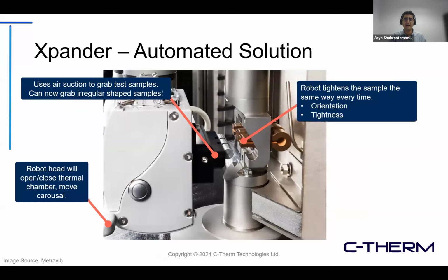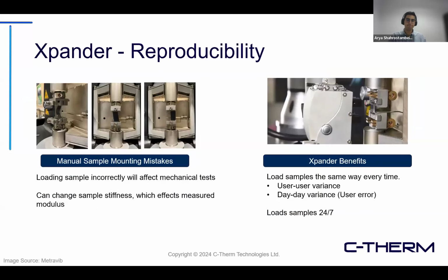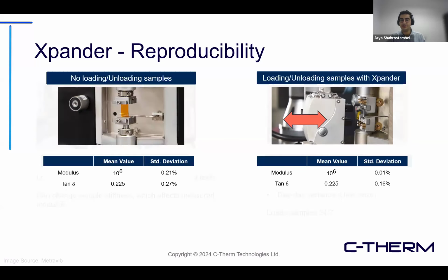Another advantage is that you can keep running your testing 24/7. Based on the information we have from running different tests, there are always human errors. A good instance of that is clamping a sample or mounting a sample on the specimen holder, which can always come with some errors and can significantly affect your measurement. So it's important to remove this error, and we can see that the automated solution has improved the accuracy of your test. As you can see, with the same numbers, on the right-hand side it has significantly improved the standard deviation for both parameters, modulus and tan delta. This option is easily provided by Metravib.